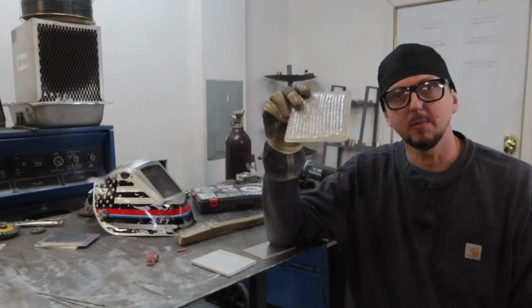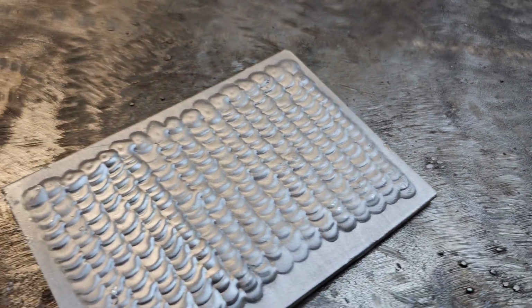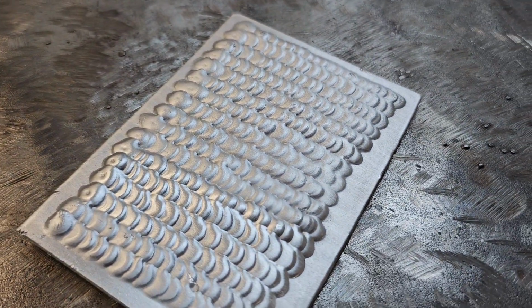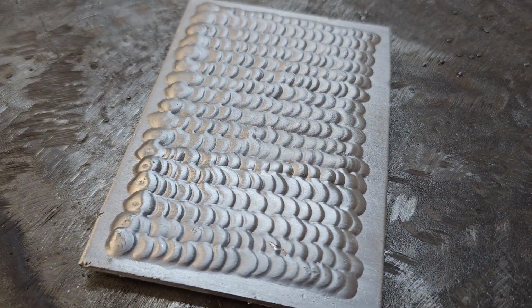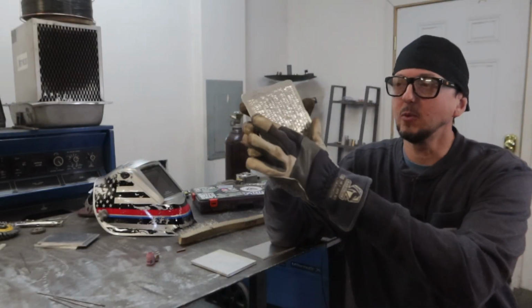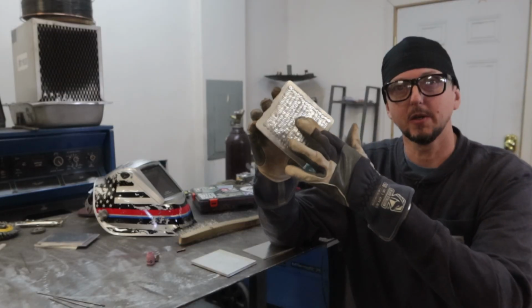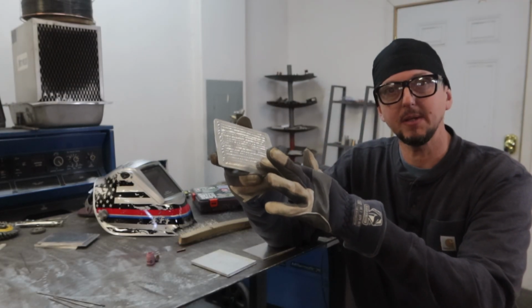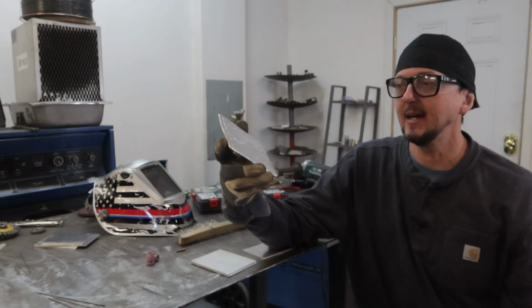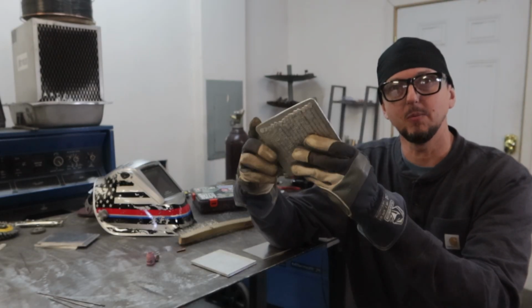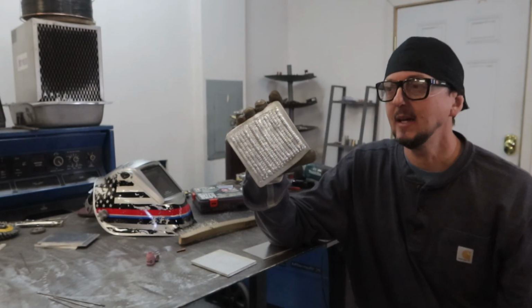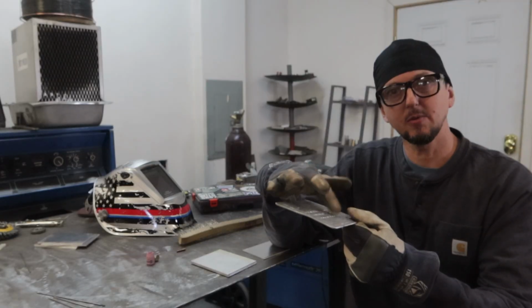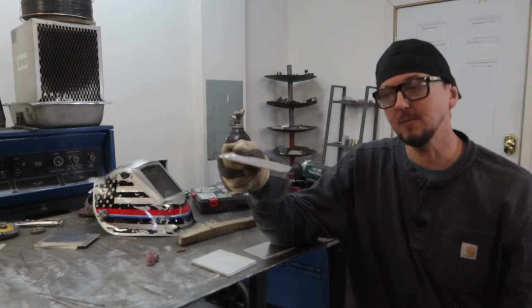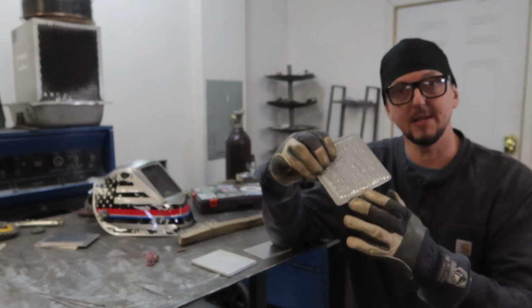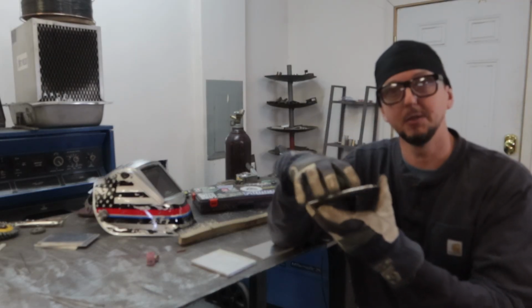All right, so the project that we're going to do to get started is this surfacing plate. Like I said before, this will give us a lot of experience welding aluminum, just putting beads on the surface. And we're actually going to create a new surface. So we're going to slightly overlap each bead and create a whole new surface here. And we can do this on both sides of the plate. By the time we get through both sides of this plate, we can even do multiple surfaces on each side, make a brick of aluminum.